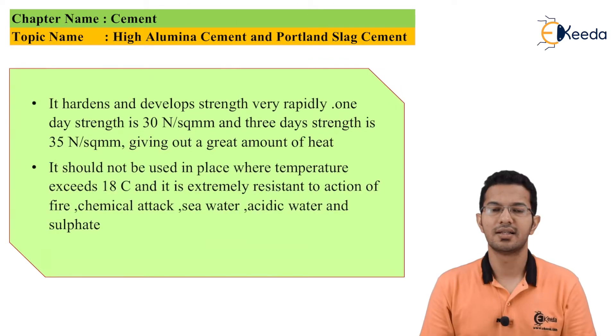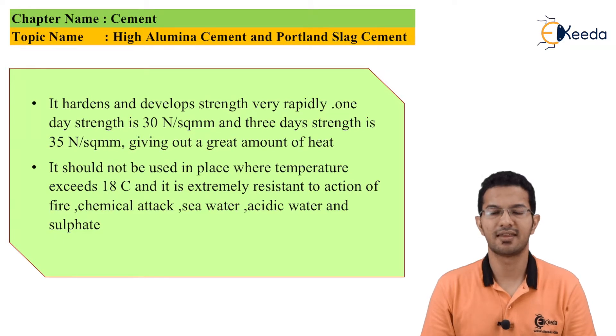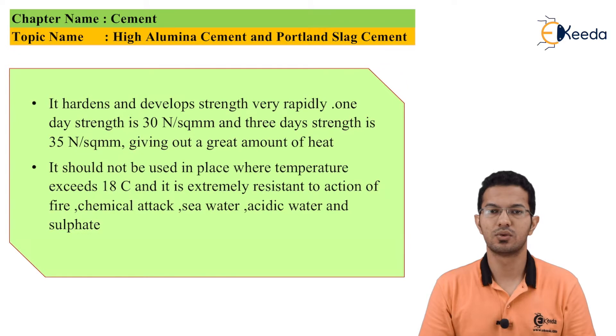Now let's discuss about strength and in which condition this cement is suitable for use. It hardens and develops strength very rapidly. One day strength is 30 N/mm² and three day strength is 35 N/mm², giving out a great amount of heat.